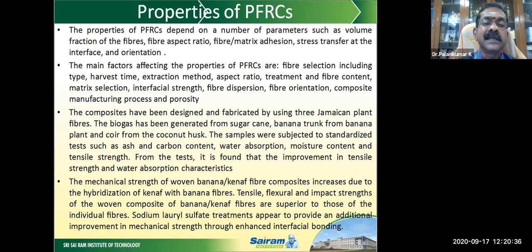The mechanical strength of woven banana kenaf fiber composite increases due to the hybridization of kenaf with banana fiber. Tensile, flexural, and impact strengths of the woven composite of banana kenaf fiber are superior to those of the individual fiber. Sodium lauryl sulfate treatments appear to provide an additional improvement in mechanical strength through enhanced interfacial bonding.